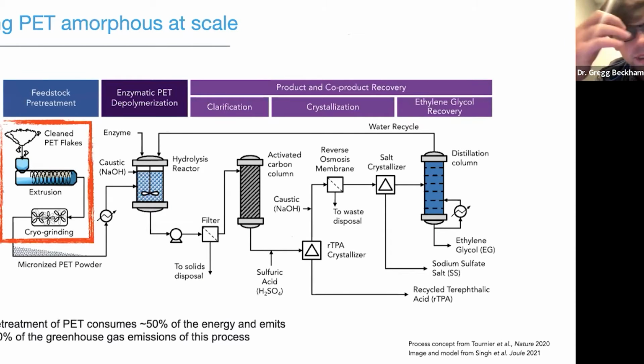This is how Carbios and others are proposing to take in both textile grade PET as well as bottle grade PET and turn this into amorphous PET that enzymes are able to work on. So, we modeled this and we published this. This is based upon the process concept from Carbios, published in Nature in 2020, as I mentioned. And this model was published by Avantika Singh in our group and co-workers in Joule in 2021, so last year. And we modeled basically the Carbios process where they take in clean flake, they do a thermomechanical extrusion of this flake, and then they cryo grind it after extrusion.